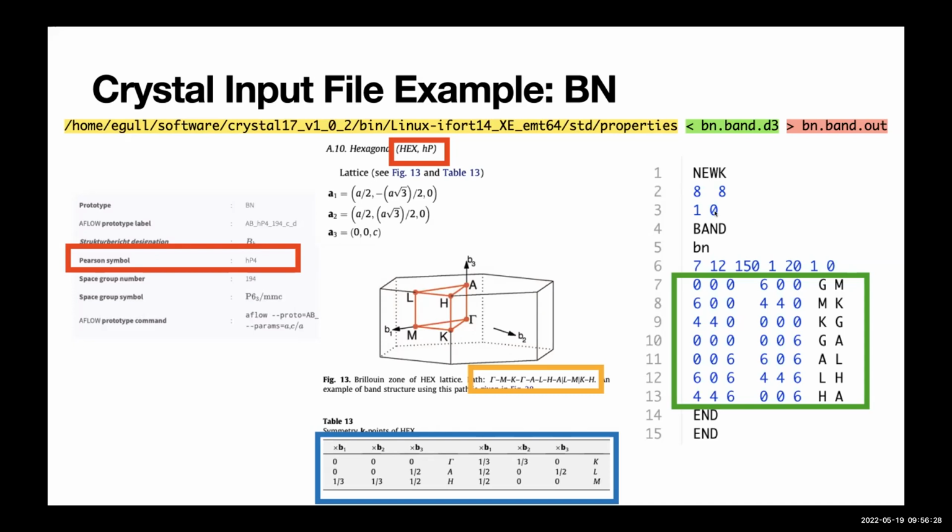If we just stop right at line 3 and add a keyword for printing reciprocal lattice information, this program will generate the original k-point set, the original A by A by A k-point set. But to plot the band structure, we definitely need the eigenvalues of k-points along the high symmetry path instead of the original k-grid. So instead, we use the keyword in line 4.